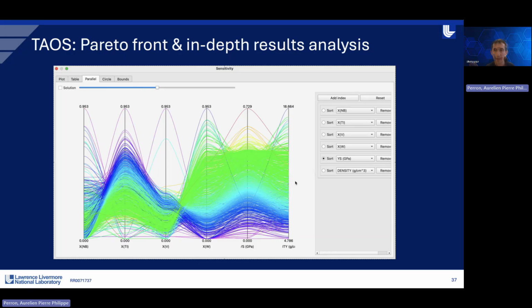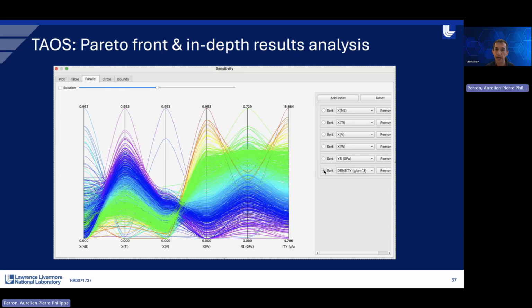But if you want to minimize density, you can sort by density. So I went a little bit fast, but here you can sort the colors of your parallel plot. So here I sorted by density. So we were interested in minimizing density. You can see that, of course, it will correspond to higher titanium content and low tungsten. But this is really to show you how you can analyze your data also within TAOS.